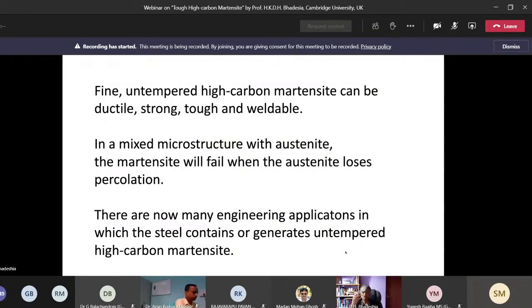So the carbon concentration has to be below about 0.48%. So we can revise our teaching to undergraduates that martensite does not have to be brittle if you make it extremely fine, and also increase the number of crystallographic orientations within a single austenite grain. If you have a mixed microstructure, then the martensite will fail when the austenite loses percolation.